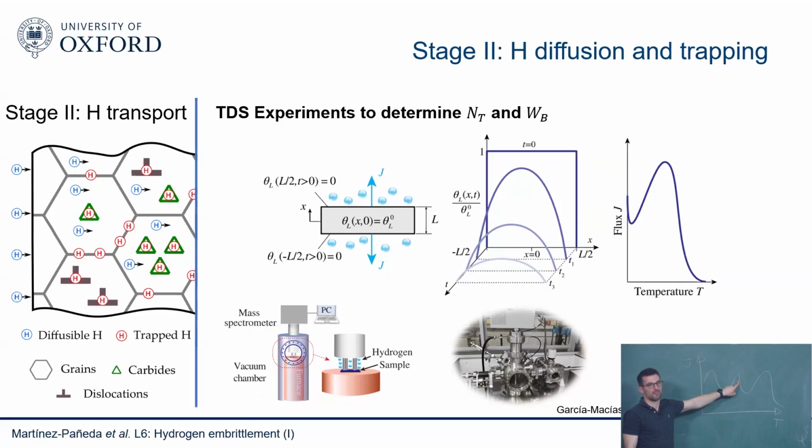This required much more temperature, so it was energetically more strongly trapped in my defect, and this was by far the biggest trap. But then you need to go from here, you get this, and then you need to say, okay, how do I correlate this with traps? First of all, you could have multiple traps in one peak, so it's not as simple as just identifying peaks.